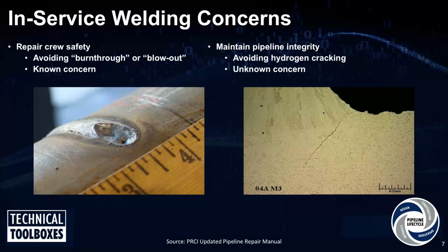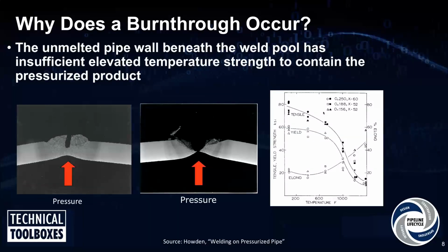So talking about burn through is kind of a little bit of a misnomer. In construction welding, there is a defect in construction girth welding called a burn through, and that's what happens when a welder is welding the root pass. Depending on the welder technique or maybe the variation in joint, the welding arc force will actually blow the weld pool into the ID of the pipe. So that's typically what a burn through is from a construction standpoint.